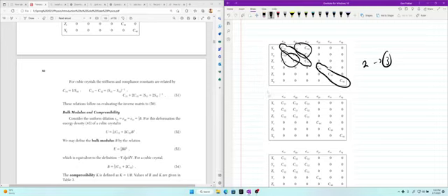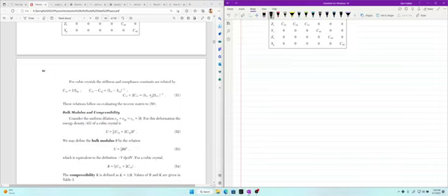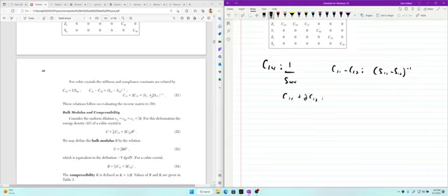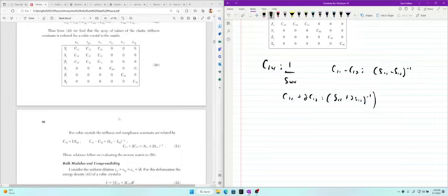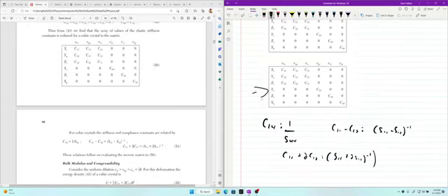And that's just by repeating all the stuff. So for cubic crystals, the stiffness and compliance constants are related such that C44 is equal to 1 over S44, C11 minus C12 is equal to (S11 minus S12) inverse. So they have the inverse relationship, because one's unit of pressure, inverse. Then C11 plus 2C12 is equal to (S11 plus 2S12) to the minus 1. And these relations follow when we evaluate the inverse of this matrix over here.